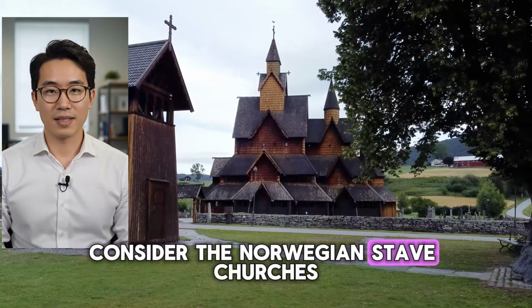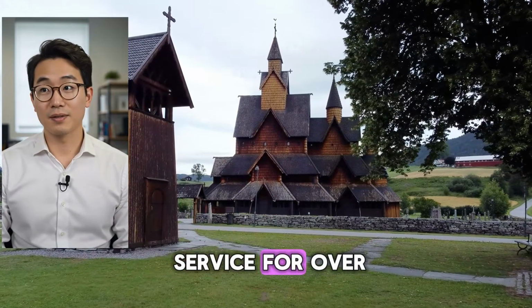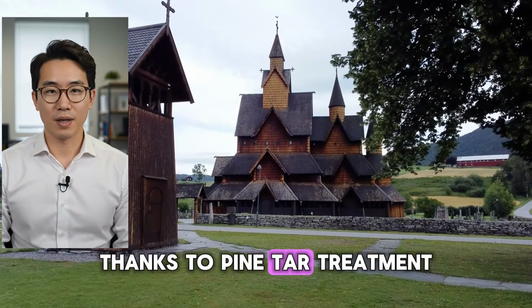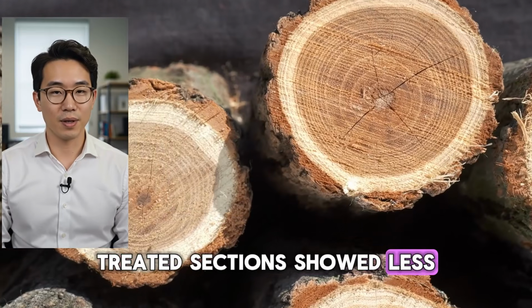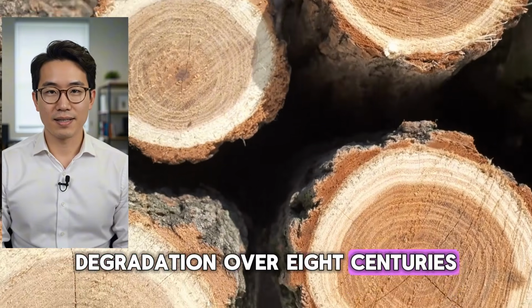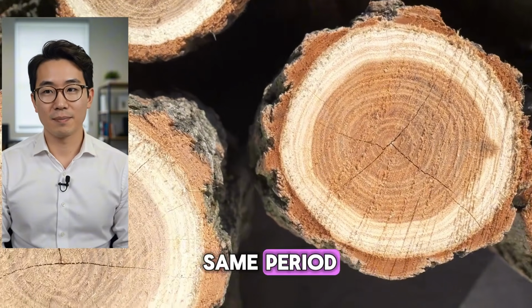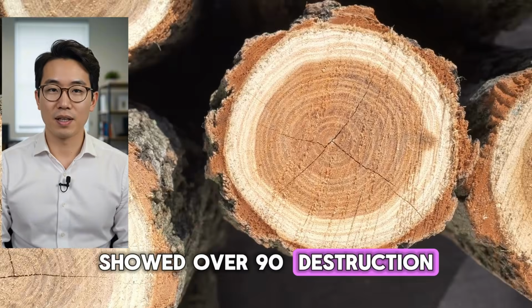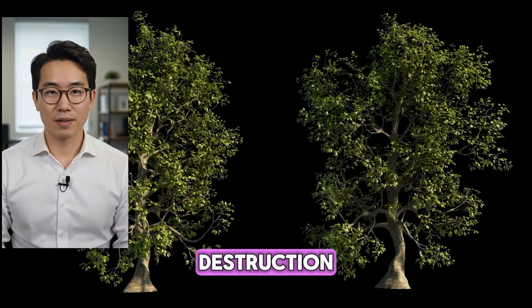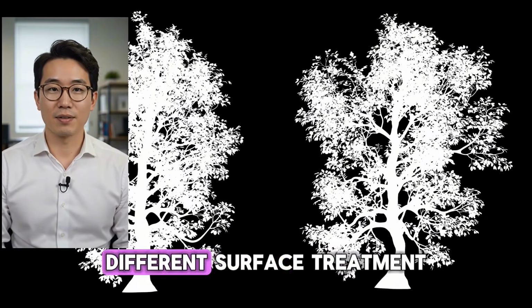Consider the Norwegian stave churches. Some have been in service for over 800 years thanks to pine tar treatment. Treated sections showed less than 12% degradation over 8 centuries. Untreated timber from the same period showed over 90% destruction. 800 years versus effective destruction. Same tree species, different surface treatment.